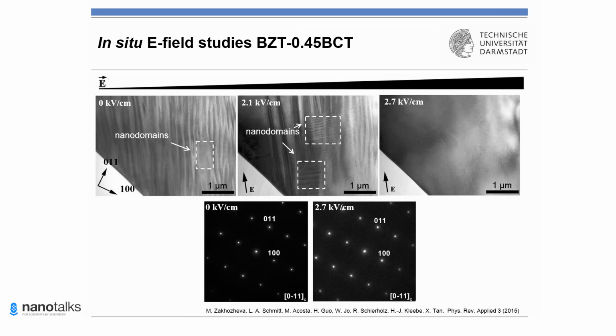For the orthorhombic BZT-0.45BCT composition, a grain oriented along the 011 zone axis was chosen for this kind of experiment, and you can see that at zero field domains oriented in the 111 direction are visible. However, within some domains you can see a further contrast, which we define as nanodomains. With increasing the poling field up to 2.1 kV per centimeter, we see that these nanodomains grow. And at further increase, the single domain state appears again. What is actually interesting is that if you compare these two diffraction patterns, there is basically no difference. There is no reflection splitting.